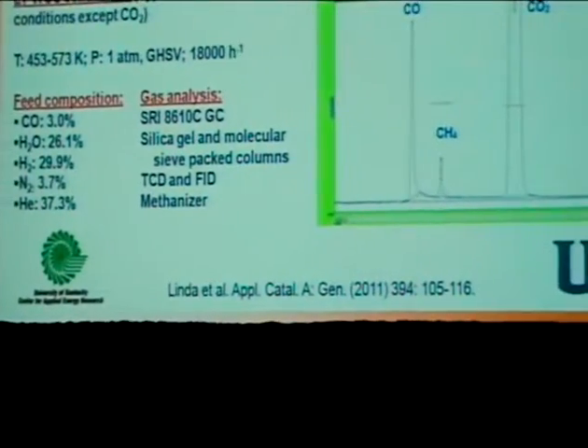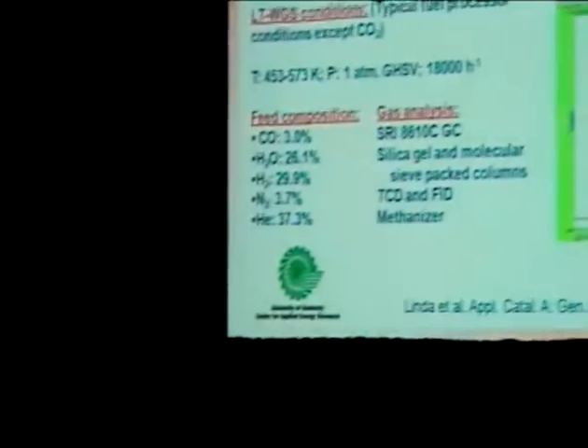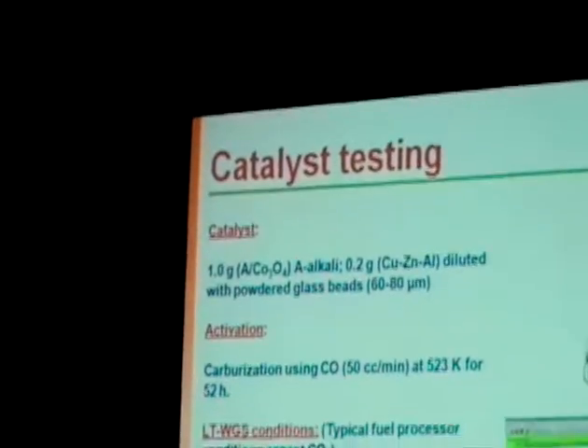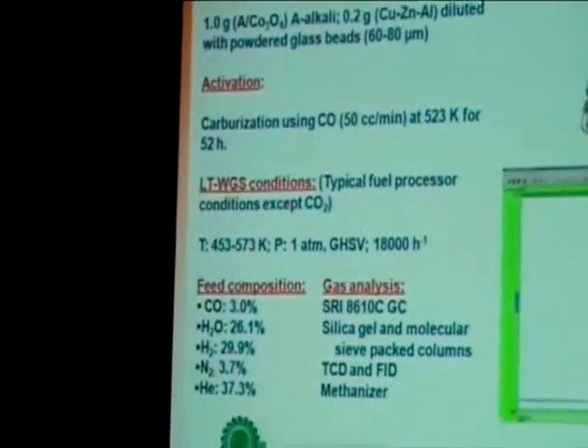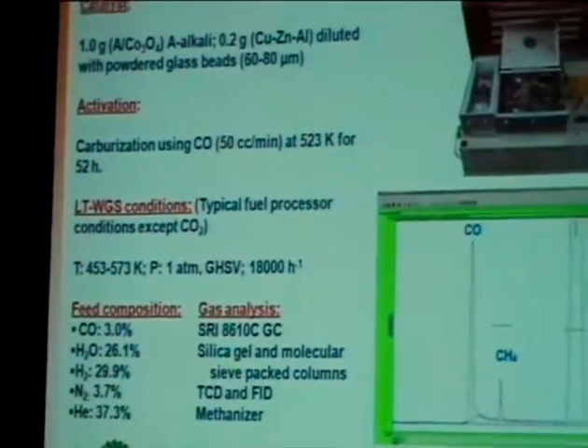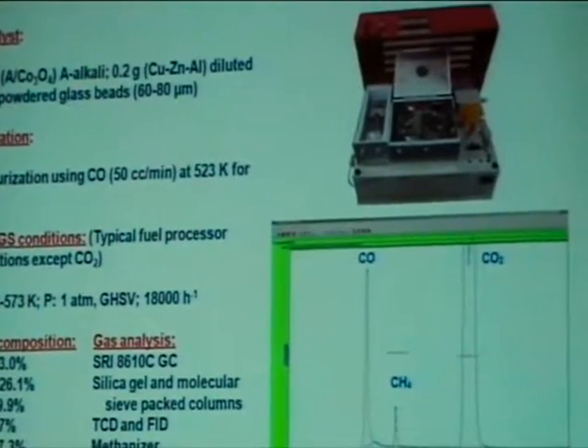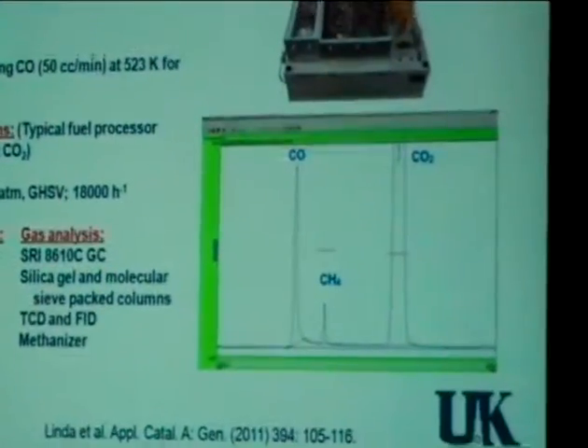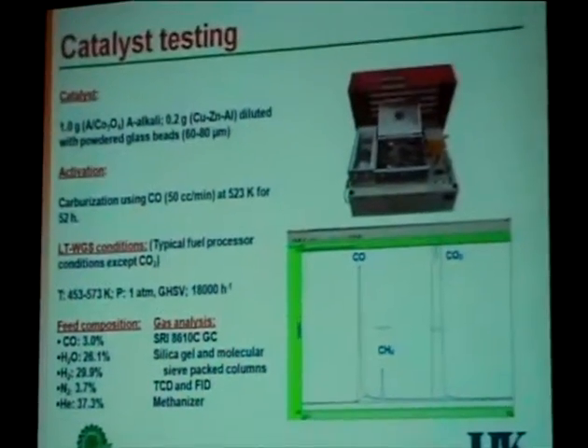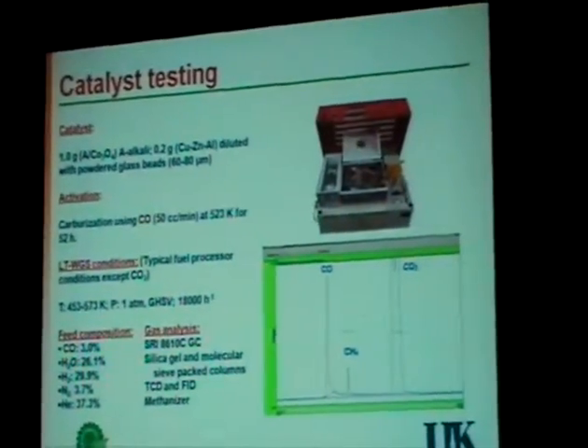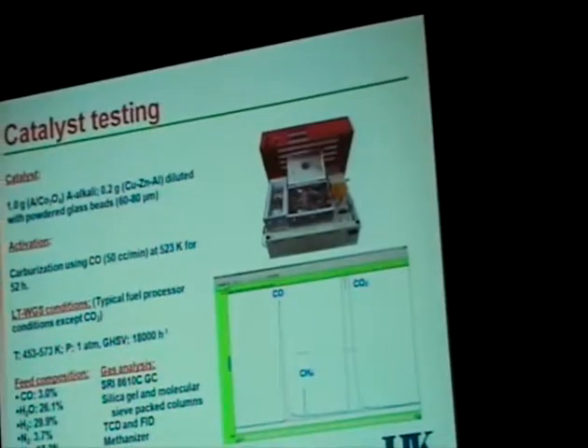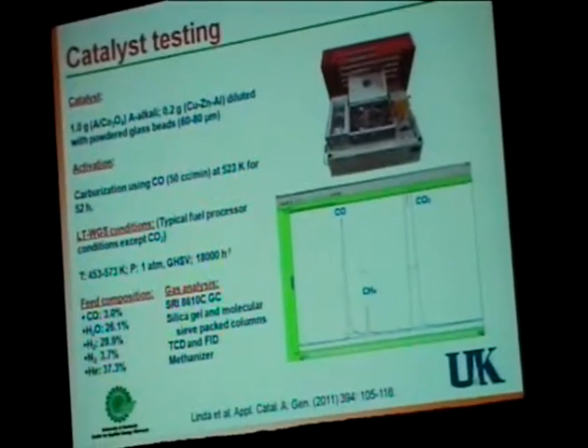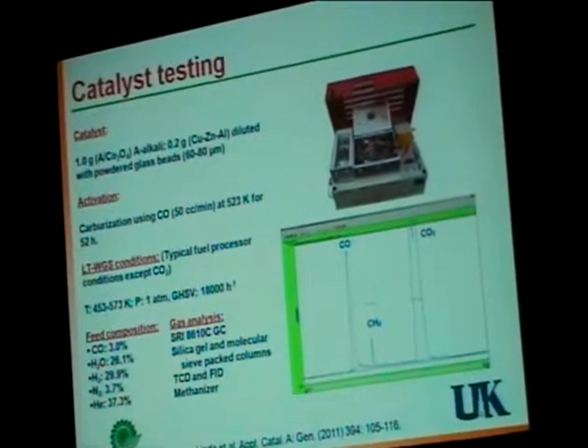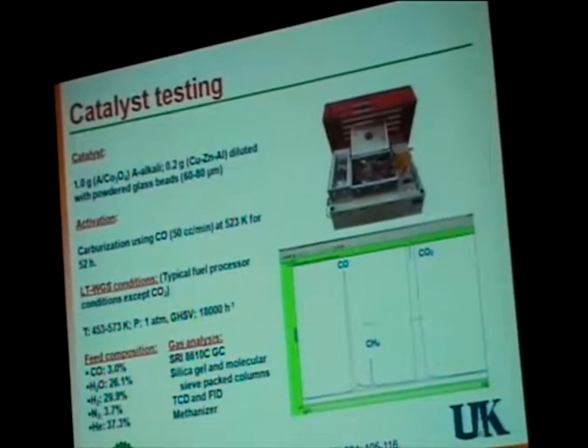So the typical catalyst loading will be like 1 gram of the promoted carbide catalyst. And in the case of copper, zinc, aluminum, which we tested for comparison purposes, it is 0.2 gram of catalyst, diluted with the powder glass in 60 to 80 micron size. And as I said, the activation will be done in situ using CO at 523 K for 52 hours. And the typical conditions for the water gas shift that we followed is the feed gas composition, typical for the fuel processor condition, except with the CO2. And of course, we did this reaction at atmospheric pressure.